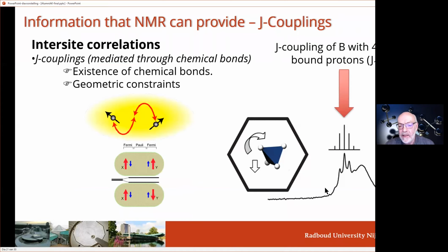But then we have this line that's split into a little multiplet at higher temperature. Actually, it's a quintuplet. So 5 different lines. And this is now the so-called J coupling of the boron via a chemical bond, because these 4 protons bind with a chemical bond to boron, and so-called J couplings are couplings between nuclei that share electrons in a chemical bond. If there is no chemical bond, there is no J coupling.